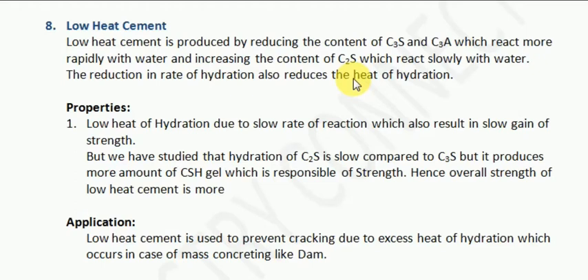The two chemicals C3A and C3S that react very immediately with water — reduce their content. And C2S, which reacts with water with a slight delay — increase its content. What will happen? Initially, when water is added, the pace of reaction will be slow. With time, the speed will gradually increase. Due to this, the heat that is released will be reduced over a longer duration, and the heat released per minute or per second will be very low. This cement we will call low heat cement.